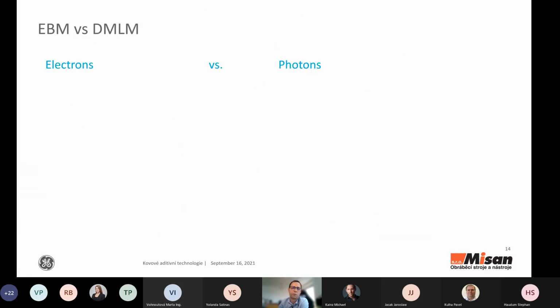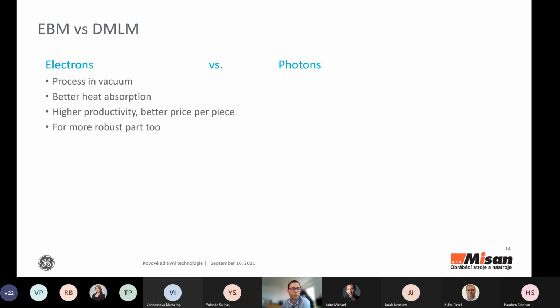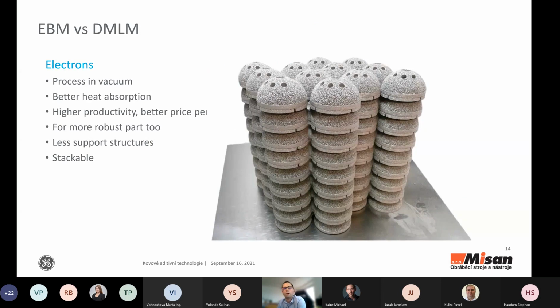So if we compare electron beam melting with laser beam technologies: the process is in vacuum. It has better heat absorption. It's usually 70% compared to just 30% for laser. It has much higher productivity due to the higher electron beam power and the movement speed. It can also be suited for more robust parts and fewer support structures. And as I mentioned, you can stack the parts one on top of the other.